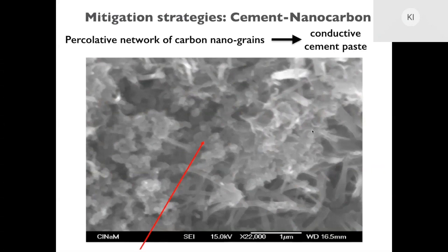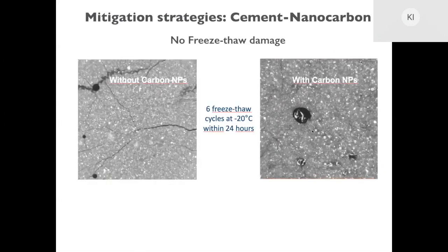We subjected this material to freeze-thaw cycles. On the left, you see the normal OPC cement with no carbon nanoparticles, and on the right, the one with carbon nanoparticles. And you can see that we can prevent freeze-thaw damage using the carbon nanoparticles. The reason we can do this is because carbon is, on one hand, hydrophobic, so we have a smaller amount of water in the material. The second thing is that these are all porous carbons, so they have pores where the ions can be stored. That's a way to reduce the ionic pressure, because these ions don't have to sit in the nanometric layer between water and ice, but can sit inside the carbon.